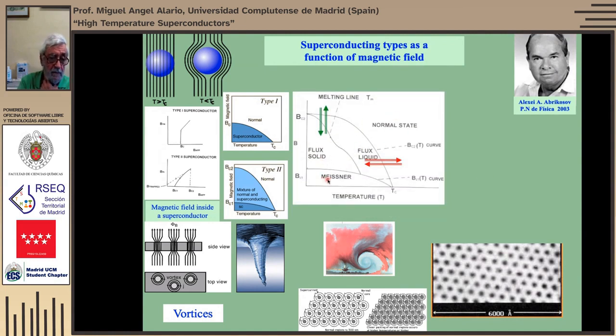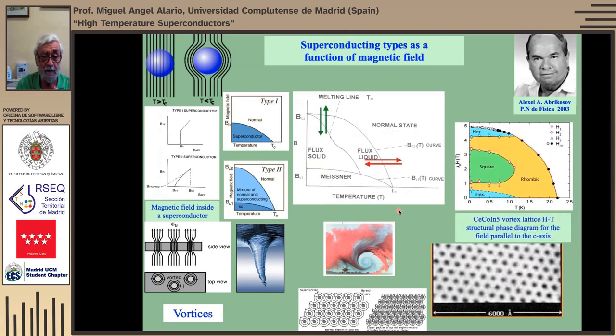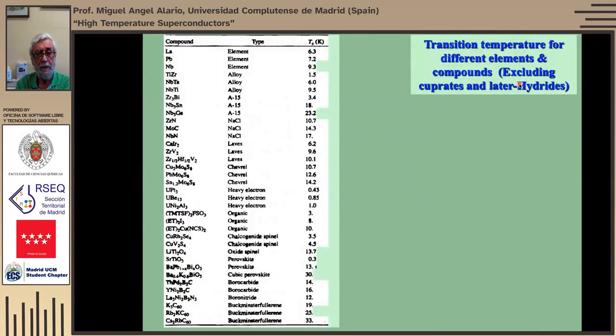You can have a superconducting state where the flux is expelled. Then here we have a mixed state that can be ordered or disordered, and then you go to the normal state. So it's a beautiful phase diagram, and it can be really very complicated. This is the phase diagram of these materials only in terms of superconductivity. So you have hexagonal, rhombic, square, hexagonal, normal, and all this in superconductivity. So it's a very interesting phenomenon.